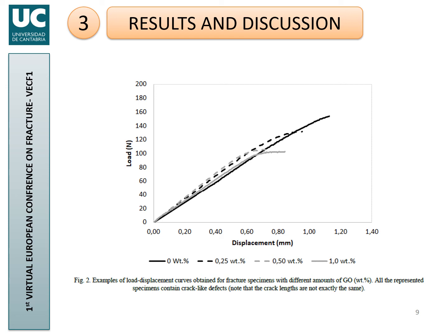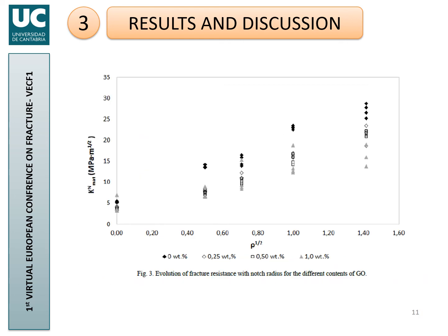Here you have some examples of the load displacement curves obtained in the fracture test. You see that the curve for the pure polyamide is much more linear, and this linearity decreases when including the nanoparticles. We represent the apparent fracture toughness. We follow the corresponding fracture standards for composites, and you may see that in the paper.